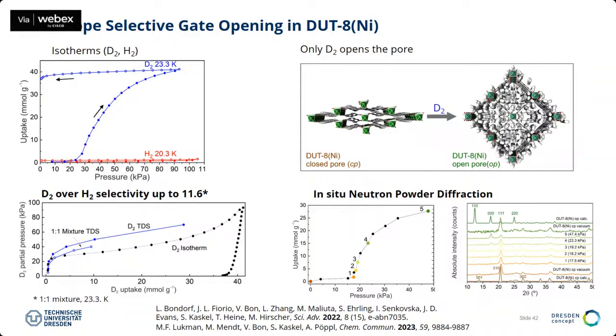But there are also other separations that have become more interesting recently. For example, isotope separation is a very hot topic. The separation of deuterium, tritium, and hydrogen, basically. Also water isotopologues, there are many studies in this direction. And we were very surprised to see that this MOF selectively opens its pores for deuterium, while hydrogen is excluded from the pores. And this is an experiment which we did at about 20 Kelvin.